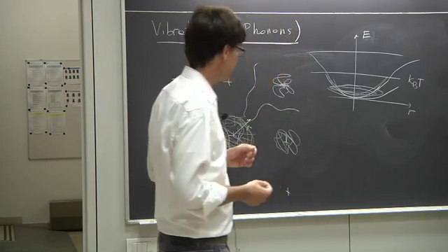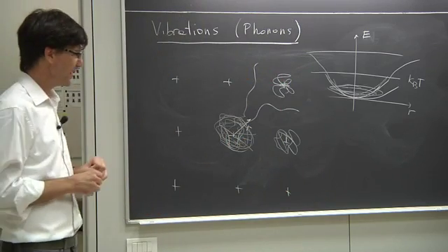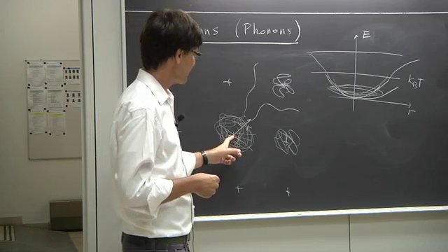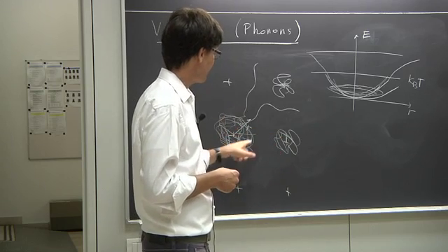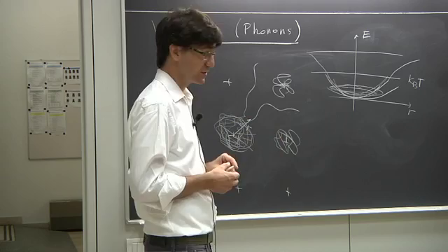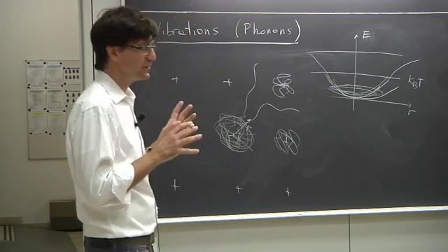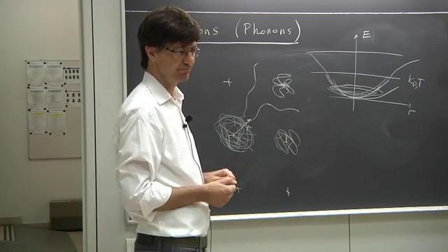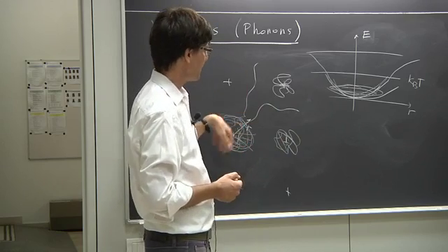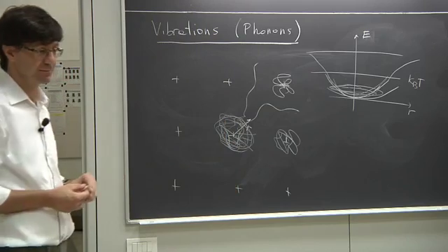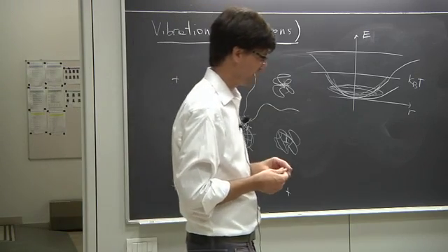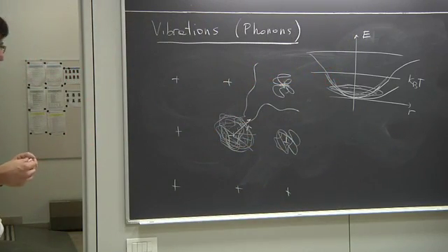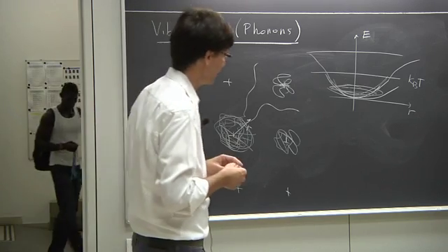Okay? In fact, there is even a rule of thumb, which is verified to an impressive precision, even though it's not a theoretical rule. And that rule states that as soon as the averaged amplitude of the vibration around the nucleus exceeds something between 15 to 20% of the distances between atoms, then the particle will begin to diffuse freely. The system will melt. There's no theoretical support for this, but it is actually verified with an impressive precision throughout the materials that we know in nature. So, well, we can take it as a phenomenological rule.